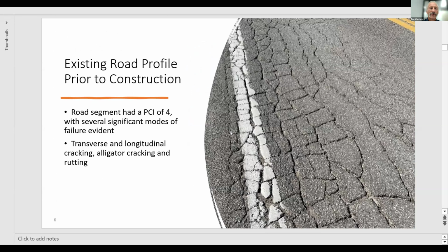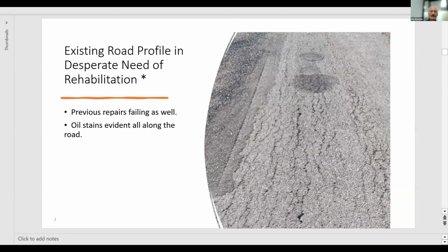Here's the existing road profile prior to construction. You can see there are several significant modes of failure evident: transverse and longitudinal cracking, alligator cracking, and rutting. Even the previous repairs were failing. So you can see this profile was in desperate need of rehabilitation.